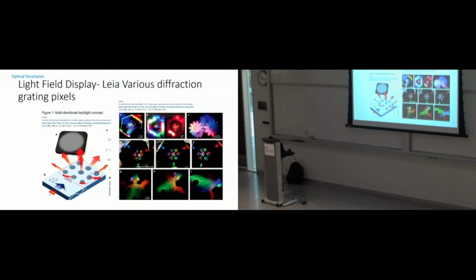And for roll to roll, you make your master molds by wrapping the PDMS film around a quartz roller. Right. Then I would expect a seam problem, right? There would be a seam there. There is a seam. We make it between displays. It depends on the size of the roller and what you want. So if you wanted it to be this wide, you make the quartz roller wide enough that the seam would be at the edge. There might be ways of shimming it. That seems a lot harder than just making a big round thing. Yeah.